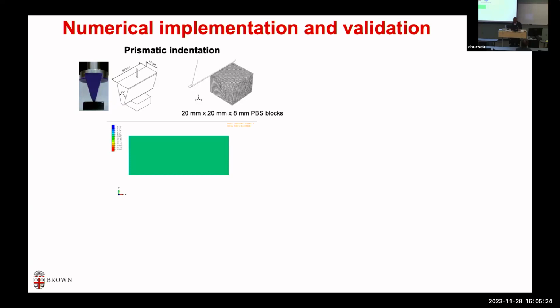There's enough meat in the computational implementation also, because the model is time dependent, right? You have to keep track of when the chains were formed, the whole deformation. The deformation gradient has 9 terms, it's a second order tensor. And you have so many elements here. For each element, for each time point, you have to keep track of the whole deformation gradient to be able to predict things at the current point, which is very, very memory intensive. So we came up with an approximate implementation where you don't have to keep track of all the history. We're only needing to know the last deformation gradient, and you can predict that. So that's all in the paper. I'm going to skip that. But nonetheless, we have implemented the model.